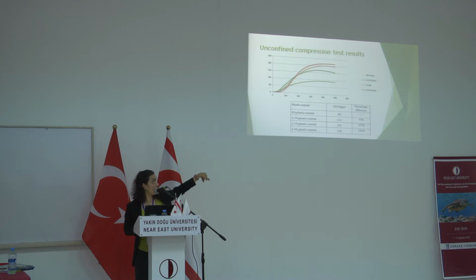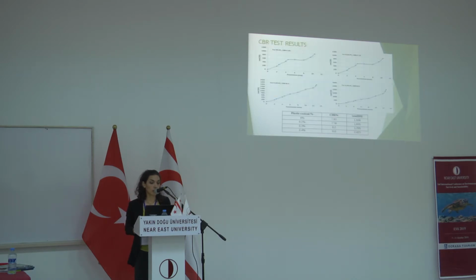As you see, the lowest curve is for the soil that doesn't have any stabilizer. So with addition of plastic, we can see that the strength is increased up to 145%. So we can see that with 0.3 and 0.4%, we have the best results. And also the CBR test, bearing ratio. We can see that addition of plastic increased the bearing ratio from 1.59 kilonewton to 2.4 kilonewton.